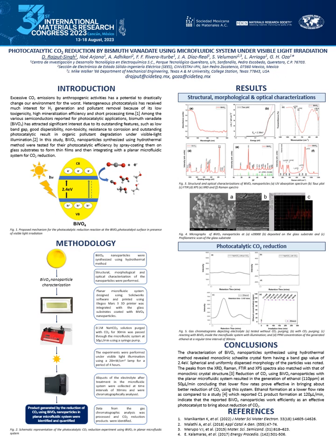Eventually, the bicarbonate solution purged with carbon dioxide was allowed to pass through the system with the help of a syringe pump, and when the aliquots were taken and analyzed, we found the presence of ethanol as a reduced product in the reaction mixture. The first peak was obtained in the first aliquot taken at around 30 minutes, and the production of ethanol continued till the 4th hour of the carbon dioxide reduction experiment.